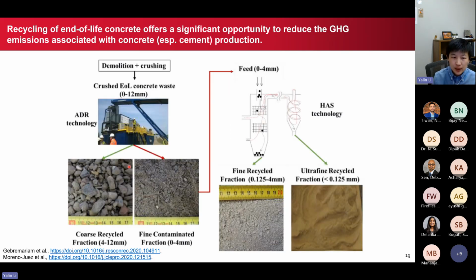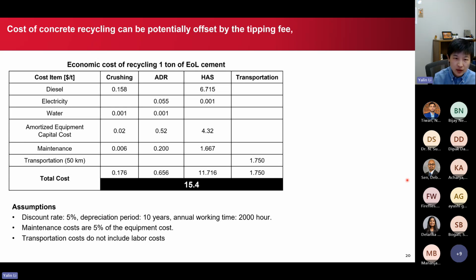So what they propose to do is essentially using the end-of-life concrete waste, you have the recycled coarse materials, and you have this further separated fine material that can be used to replace the fine aggregates, and then you have this ultra fine part that can be used either as a filler or as a direct replacement of the cement part. So we did some rough cost estimations of these technologies. In order to recycle 1 ton of concrete, all the costs add up to around $15 per ton.